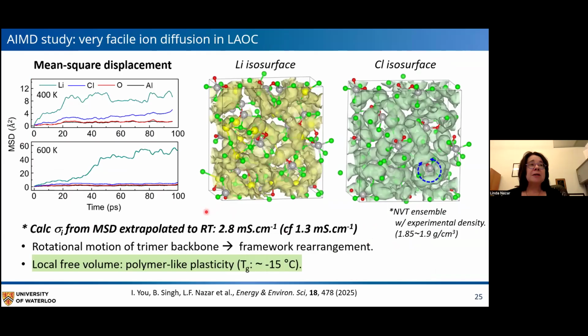And again, AIMD carried out by Baltesh Singh, my postdoc, shows that we have a calculated conductivity on the order of 2.8 millisiemens, which is really quite similar to what we measure. And this shows the lithium isosurface and the chlorine isosurface. You can see that there is, again, very high diffusivity of the lithium in the system.